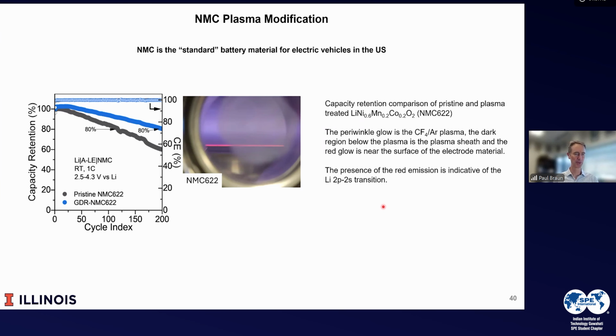So what I had shown you so far was treatment of lithium cobalt oxide. Lithium cobalt oxide is interesting. It's used in a lot of handheld devices, but it's a little bit expensive. And so NMC is a very popular system. NMC is found in many automotive batteries in particular. And what we see is that the plasma treatment also provides substantial improvement of NMC. And so that's very significant because NMC modification is probably more technologically important than the LCO. And this is actually a side view of the chamber, and this sort of reddish glow is indicative of lithium. And so this reddish glow implies that some lithium is probably being removed from the structure as the carbon and fluorine is being inserted into the structure.